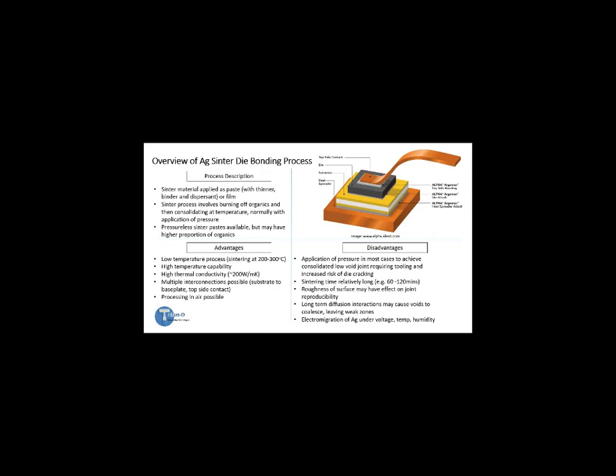And with a silver sinter material, pressure to achieve low voids is a debate which continues, and there's a whole range of materials around, which could be in film form or paste form to use. Sometimes the sintering time is relatively long. Roughness of the surface may have effects on the joint reproducibility. And I think the last 2 points, as we're pushing towards higher temperatures, are long-term diffusion interactions and electromigration, areas like that, which could leave weak zones within the modules.